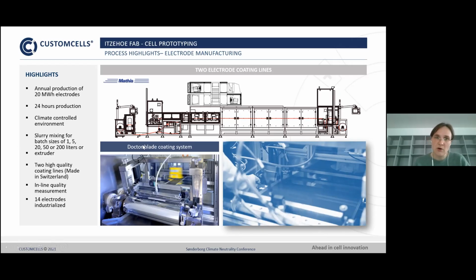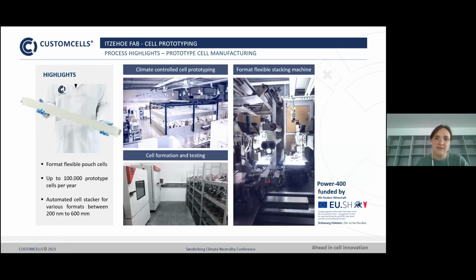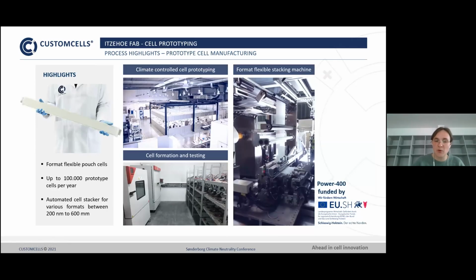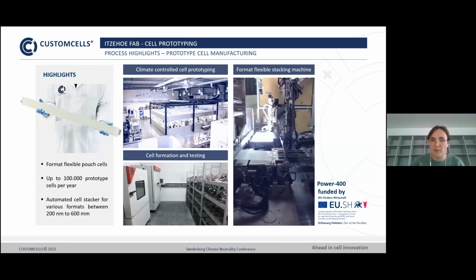And here you can see the overall machine. There is the bare foil. Here is the coating line. There is the IR drying zone. There are 2 or 3 hot air drying zones. This is our cathode coating line. We have another for anode coating. And here, after an inspection, there's just the winding again, and then you have a roll-to-roll process. So after that, you have electrodes, and what you do with the electrodes is now building up a cell.